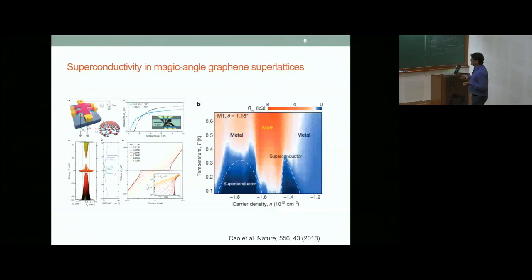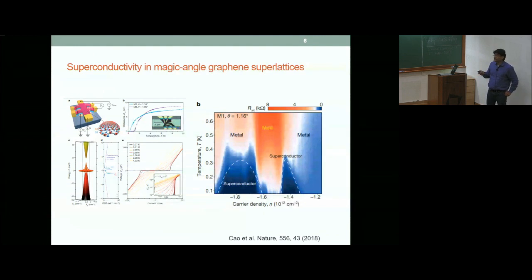So, in the last roughly 15 or 16 months, there has been a dramatic new entrant in the graphene quantum transport world, which is twisted graphene, which is two layers of graphene stacked on top of each other. And they're the biggest advertisement for the key role of controlling symmetry, which is by controlling the angle and the electric field perpendicular to the two layers. You can realize very complex states of matter, correlated insulators, and right next to correlated insulators, superconducting states. So, what graphene didn't really have in adequate measure is this: interactions really come to the fore when you look at few layers of graphene.